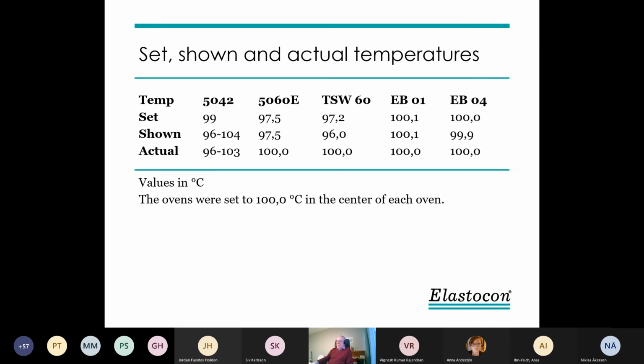Another test we made was that we put a PT100 sensor in the center of the ovens. Then we adjusted the oven so that the sensor showed 100 Celsius. And then it happened that the set point was quite different. And the temperature shown on the oven was also sometimes not the same as the set point, but they were all different from the 100 in the center, except for our own ovens, where we can keep it quite close to the desired temperature.